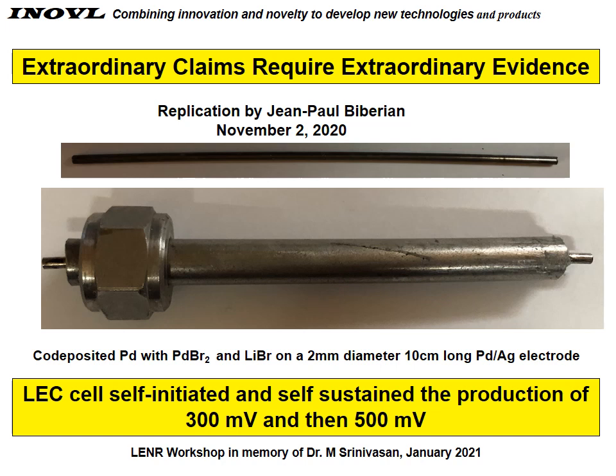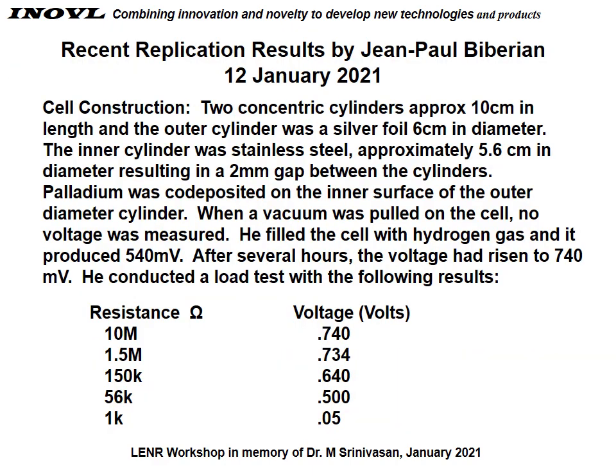Unfortunately, his first attempt did not work. He contacted me, and I suggested that he co-deposit a layer of palladium onto the palladium silver rod. He did that, and 2 days later I got an email from him with the subject line, "Success." He had reassembled the cell, filled it with hydrogen, and it started producing 300 millivolts. Then, after a little bit of alcohol vapor got into the cell, it went up to 500 millivolts.